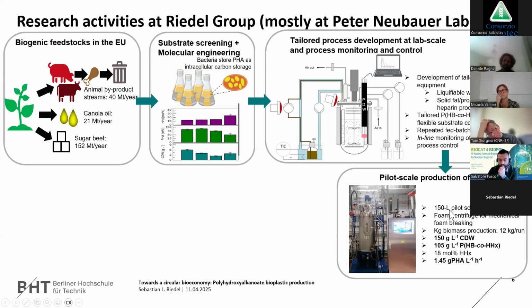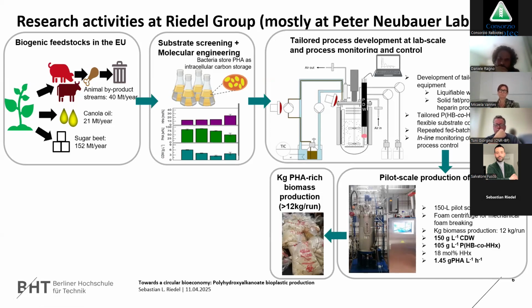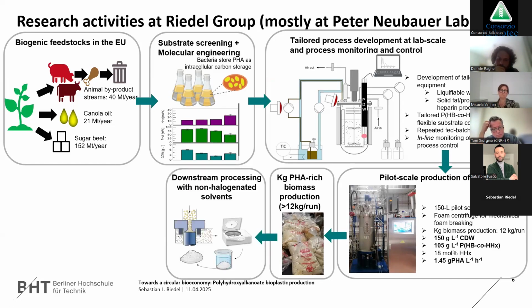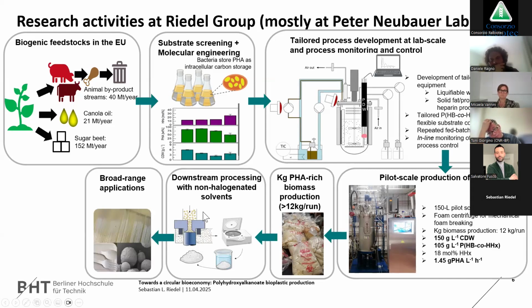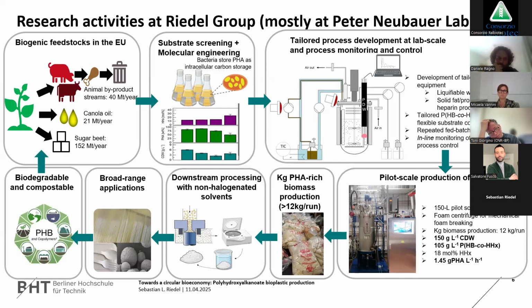And for the data we are showing, we are at 150 gram per liter, where we can produce PHA in a kilo scale for partners to testing. But right now we are also increasing this to 300 gram. And this is how the cells look like after drying. We also work on downstream processing, either from dry cells or from wet biomass, and then with partners again for formulation for different kinds of products, and also with partners for biodegradation.